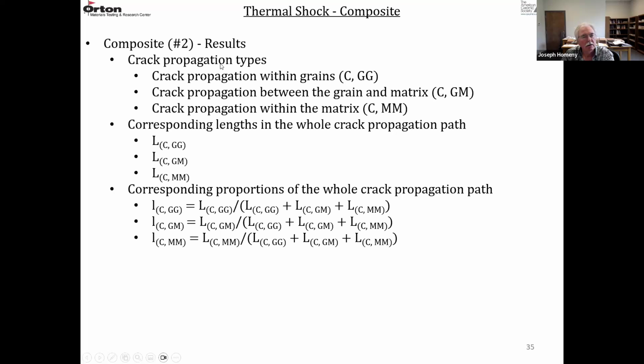So they looked at the crack propagation types. So you can have crack propagation within a grain, within an MgO grain. They label that CGG. You can have crack propagation between the grain and the matrix. They label that CGM. And you can have propagation of cracks in the matrix. That was CMM. So GG is in the grains, GM is at the interface, and MM is in the matrix.